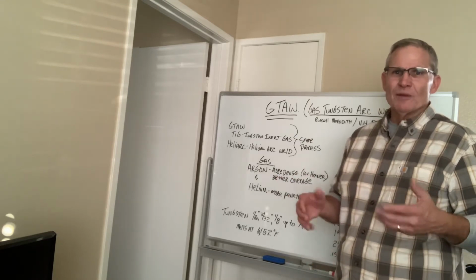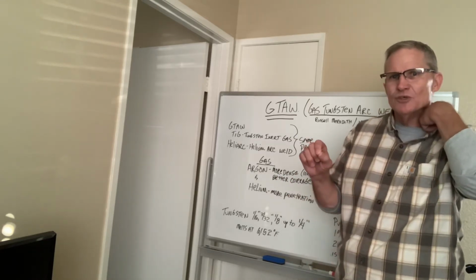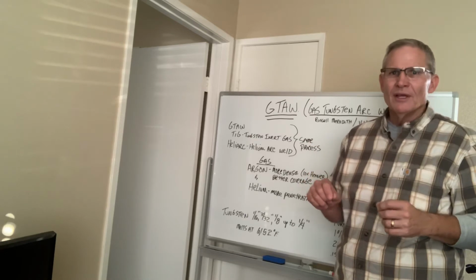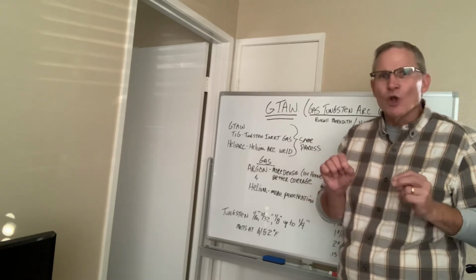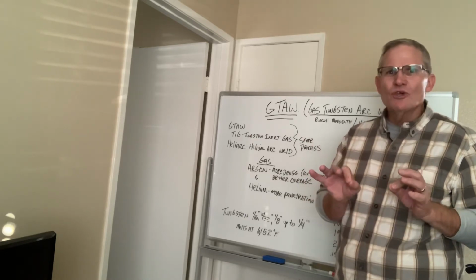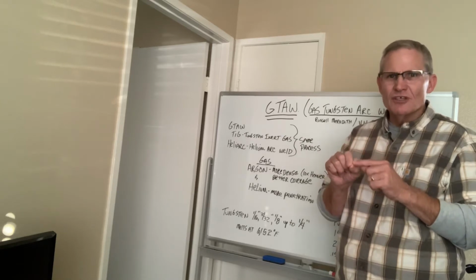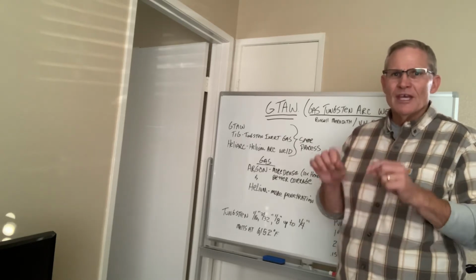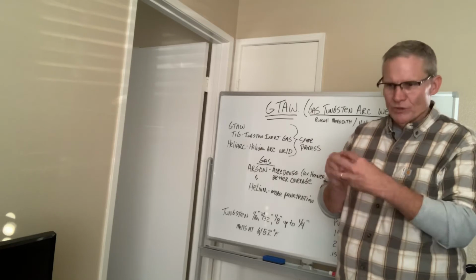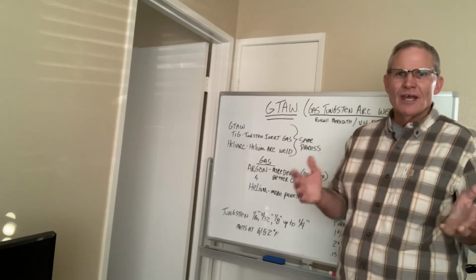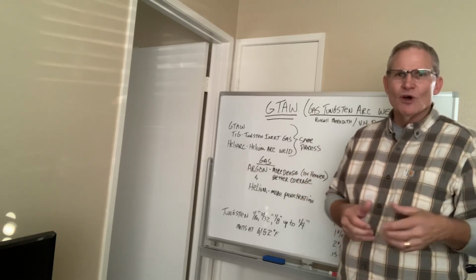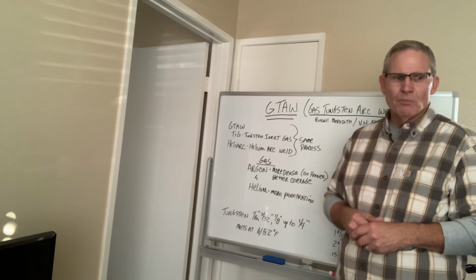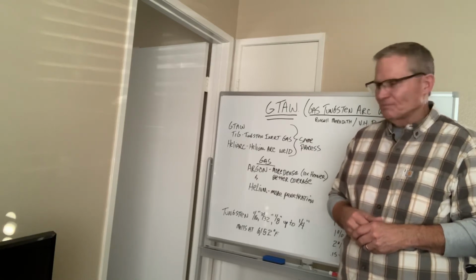When you're first learning the process, you kind of dip it into the molten puddle. Some people ask, well, how close can I get? You can get as close as you want, as long as you don't touch the tungsten into the molten puddle. If you do that, the molten puddle will jump onto the tungsten and it gets contaminated. So you'll have to grind another point onto the tungsten.